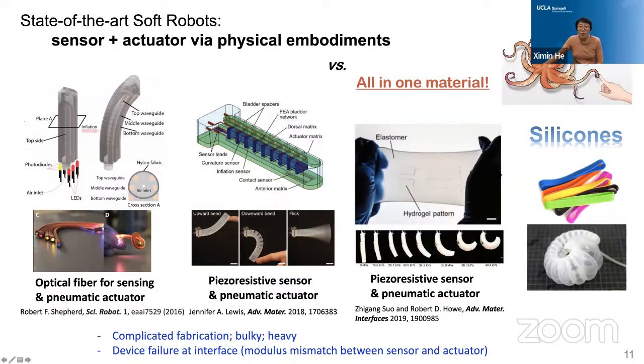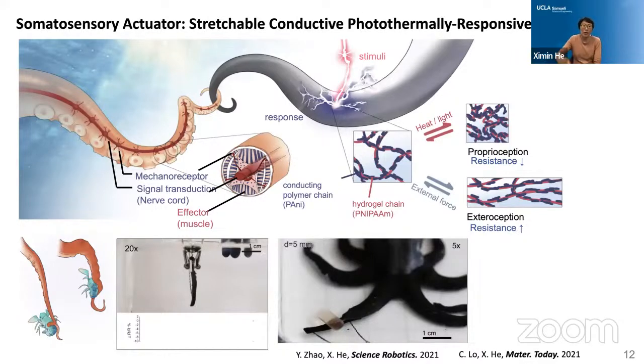Therefore, we try to develop active materials based on hydrogel to integrate both sensing and actuation ability at a molecular level. In this example, we use the very well-studied thermal responsive hydrogel PNIPAM, and then we co-polymerize a conducting polymer, polyaniline as an example here, into a homogeneous conducting and photothermal responsive hydrogel. Because this conducting polymer is black in color, it's a natural photoabsorber. Therefore, the absorbed light can be converted into heat to trigger thermal contraction upon heating, right? So this material can be a nice photothermal actuator.